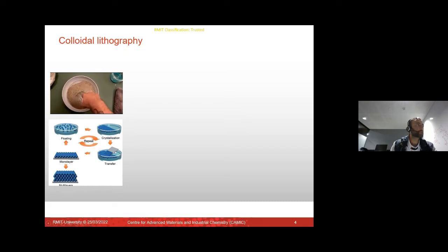We then go and put our transducer into that solution and pick up that monolayer surface, and we end up with a transducer that has the monolayer of our template polymer or colloidal structure. We can repeat this if we like and get multi-layers, but in this talk, we're not going to be presenting that. We're just going to be looking at our monolayers.